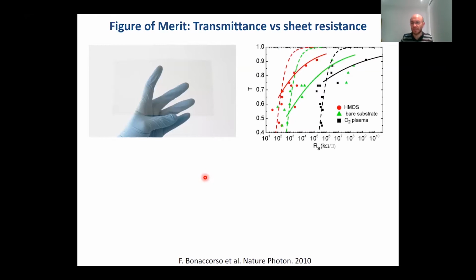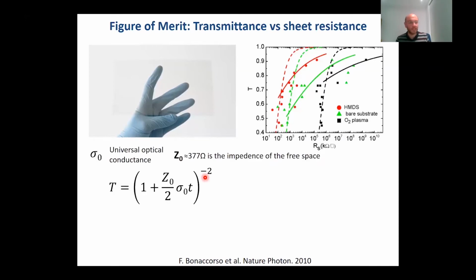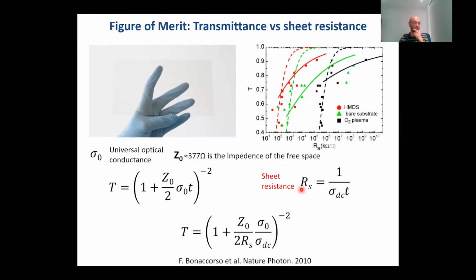Of course, we try to understand this a bit better to also describe what's happening and improve our devices. So one of the figures of merit in thin film technology is transmittance over sheet resistance. This is very well described by the thin film limit equation, where you consider the transmittance due to the optical conductance and the impedance of free space. And if we couple this with the sheet resistance, you can get this nice feature where you have transmittance over sheet resistance, and then you have a ratio of actually two figures of merit. One is the optical conductivity and the other is the conductivity in DC.